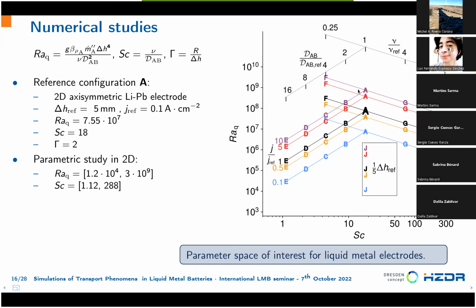Then we change the diffusivity, the viscosity, and the current density in order to do a parametric study. And we collect all these different points in the parameter space: flux Rayleigh number, Schmidt number. We also tested a case in which the height is 1/5 of the height of the layer. So we assume for the reference case 5 millimeters, and these cases are with 1 millimeter. So very thin layers. And this allows us to cover a very wide parameter space that is also useful for other alloys used in liquid metal electrodes.